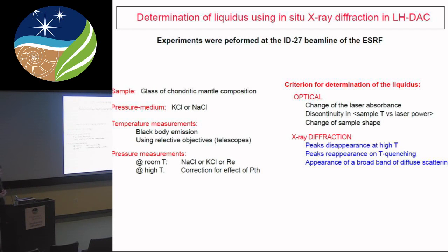Here I'm more concerned in this talk with the Liquidus determination. The solidus is of secondary importance. The Liquidus is more difficult to measure than the solidus. The solidus is the first change in the mineralogy, with a loss of some diffraction peaks or rapid change in intensity, so the solidus is relatively easy to determine. Liquidus is more difficult because you want to see the last disappearance of a phase in a given composition. Or if you go from the melt and cool down the sample, which is possible using the laser, you want to see the first appearance of the diffraction peaks, but there are temperature gradients which make it difficult. So determination of Liquidus is not very easy, it's difficult in the diamond cell.